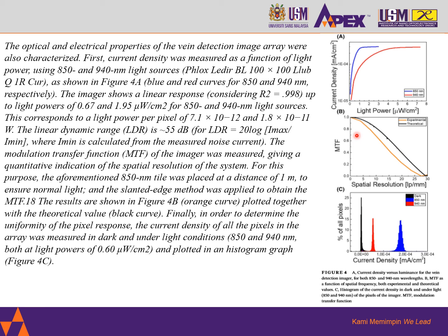Finally, in order to determine the uniformity of the pixel response, the current density of all pixels in the array was measured in dark and under light conditions, 850 and 940 nanometer, both at light powers of 0.60 microwatt per centimeter square, and plotted in a histogram graph, figure 4c.